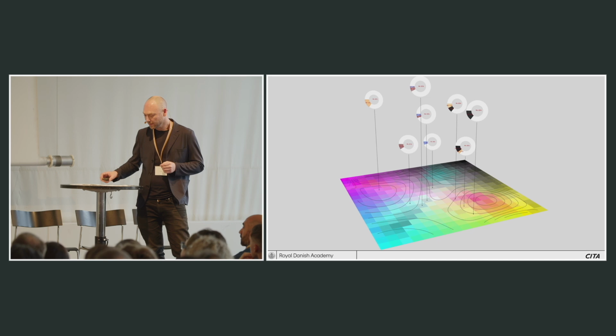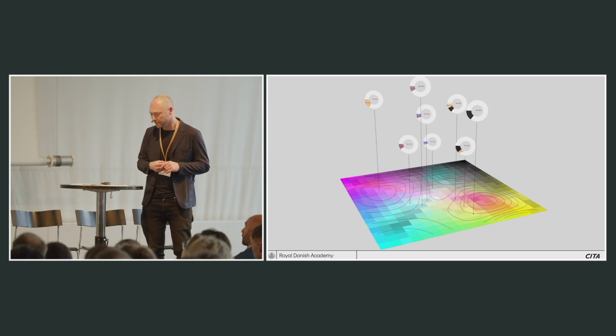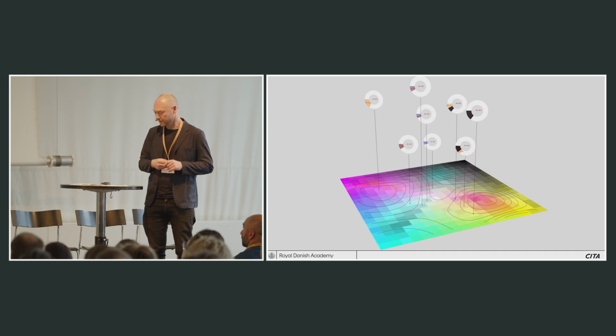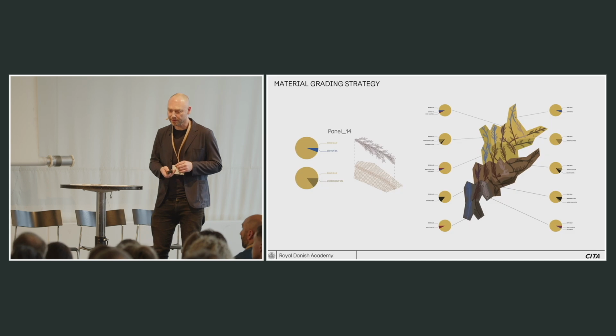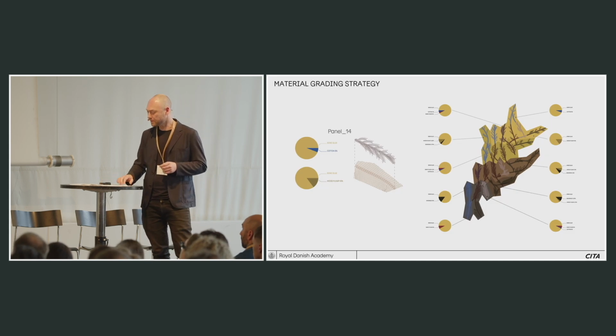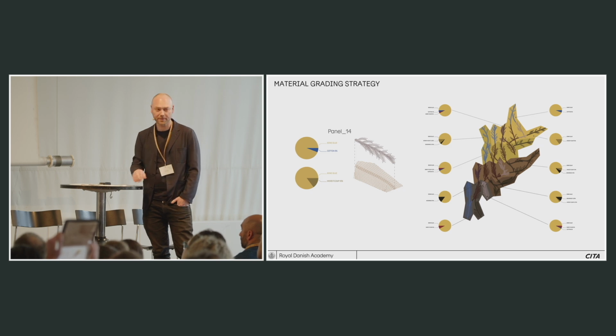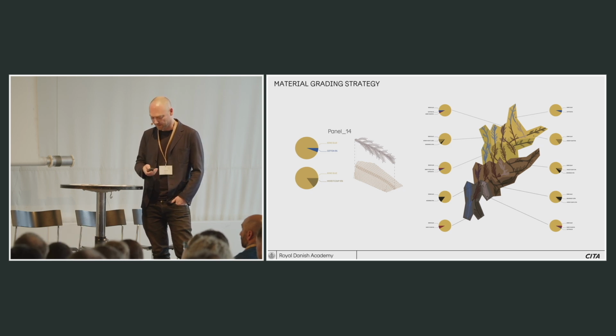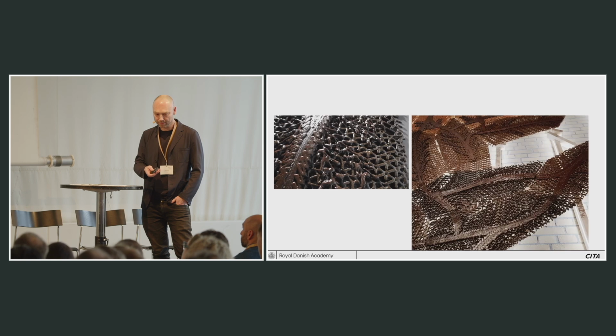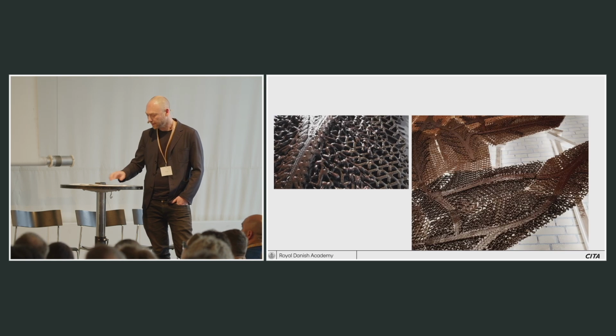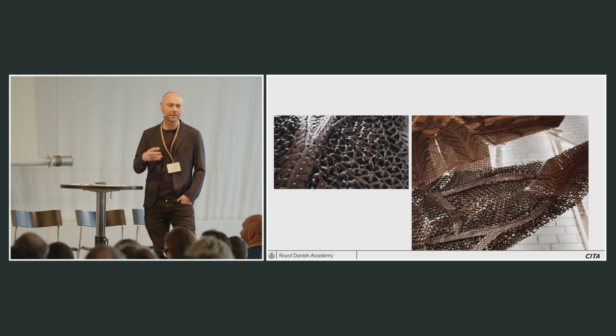In this case, materials are sampled from that recipe space for their structural properties, where several alternative materials are actually used where similar properties are found. And then we also sample that material space to achieve a stepped color gradient through the infill areas of the panels as they move up the height of the wall. Here you see the two sets of specifications that inform each of those panels, and then their combination within single consolidated printed panels.